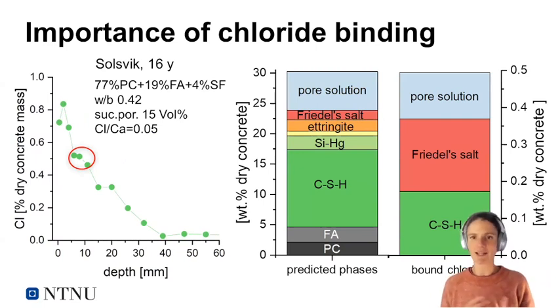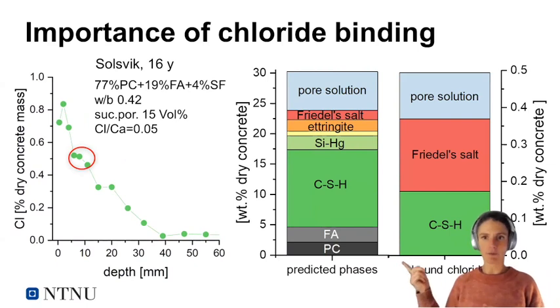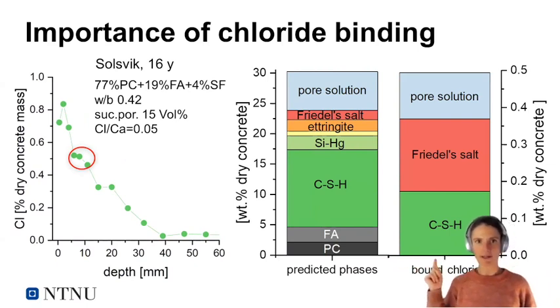I just want to illustrate the importance of chloride binding in these chloride profiles. So I took a chloride profile here from Solsvik, which was the exposure site with the beams hanging from the ferry dock. And this is a profile after 16 years. The binder composition is mentioned there. It contains a bit of fly ash and some silica fume.